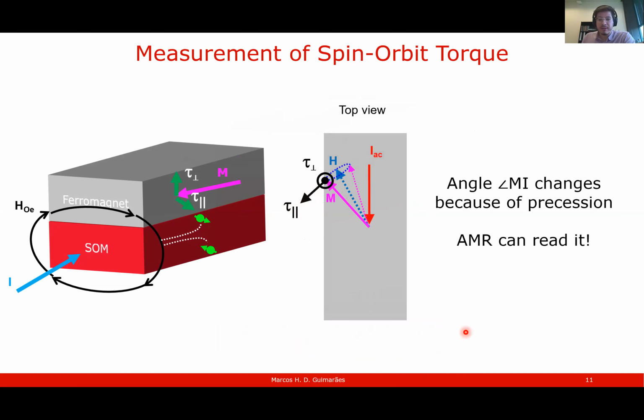Now, how do we read the torques? We read using AMR, which can convert the angle that the magnetization makes with the current into a changing resistance. So as we apply the current, this current applies a torque in our magnetization, and this torque makes the magnetization change its angle with respect to the current, and then we can read this angle through the resistance of the device.